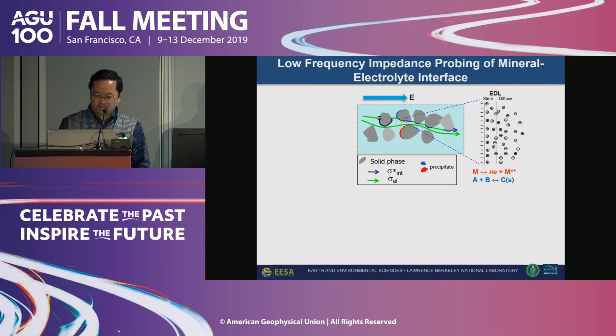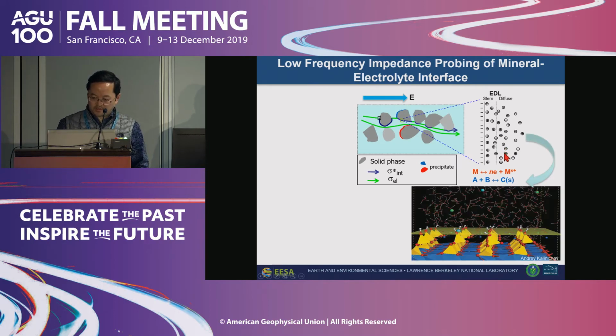Looking at the low frequency impedance wave, what you're really looking at is the charge transport behavior in porous media. When you apply a low frequency energy, you have charge going through the interconnected pores, and also charge moving at the mineral interface, which is linked with the charge behavior in the electrical double layer. When you have mineral precipitation or dissolution reactions, you modify the electrical double layer properties, which gives you a change in the signal. So again, there is a link to the interfacial structure.